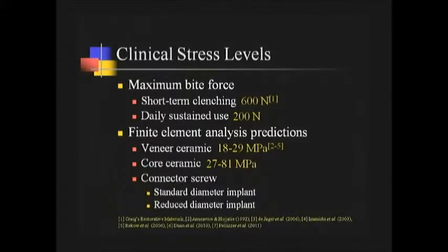Well, studies have shown based on finite element modeling that in the veneer layer of all ceramic restorations, these are probably inducing stresses from 18 to 29 megapascals, depending on the angle and location of load application, as long as we're not talking about parafunction or trauma. And the core ceramic, a little bit higher stress levels. And again, finite element modeling studies have predicted for implants.